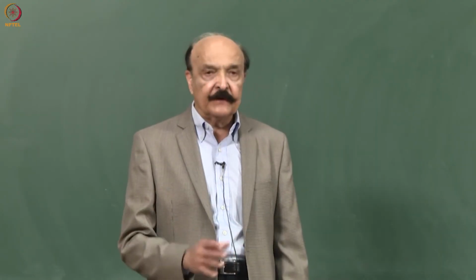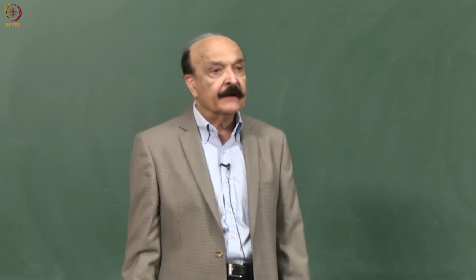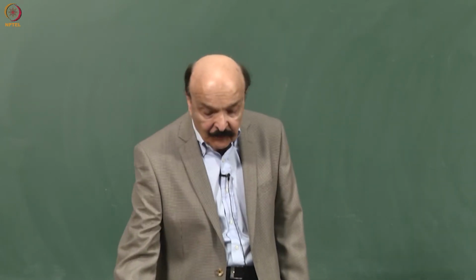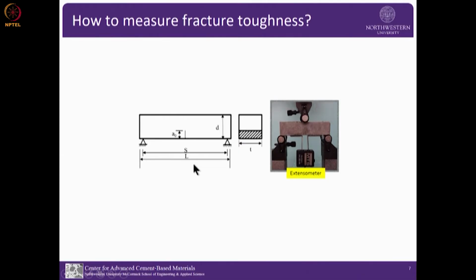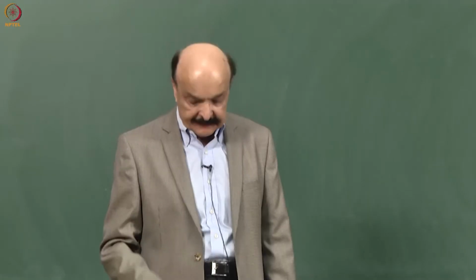And so there is a lot of work done. I think Professor Gettu has also been involved. Now I think people conclude the best way to get the fracture toughness experimentally is to have this notched beam test, and you test it with crack mouth opening displacement. When you apply the load with a CMOD control rate, you get the entire load displacement curve, and from there you can calculate fracture toughness. So this is really an accepted way. Italians have a code based on this test.